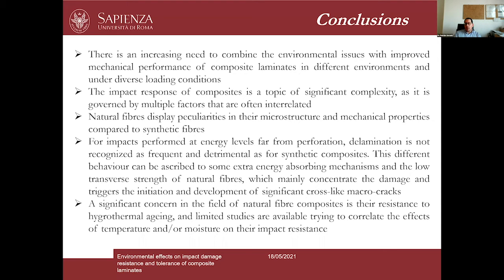A viable solution to mitigate the environmental issues could be the use of natural fiber composites. But as we saw during this presentation, these kinds of composites show pretty particular behavior in terms of their microstructure and also their mechanical properties. And if we focus on the impact response of these natural fiber composites, we can say that in this specific case, usually delamination is not envisaged as a significant failure mode, as it happens in synthetic composite materials. And this is mainly due to the fact that these natural fibers show a pretty low transverse strength that tends to localize the damage and triggers the development of significant macro cracks.